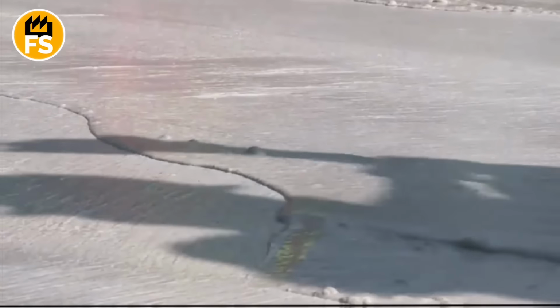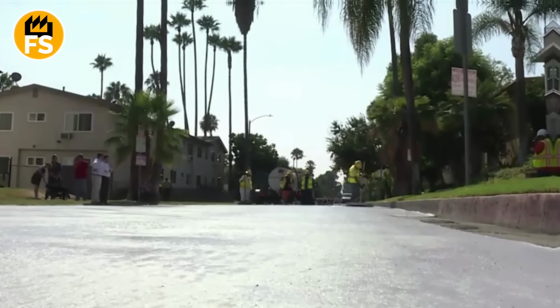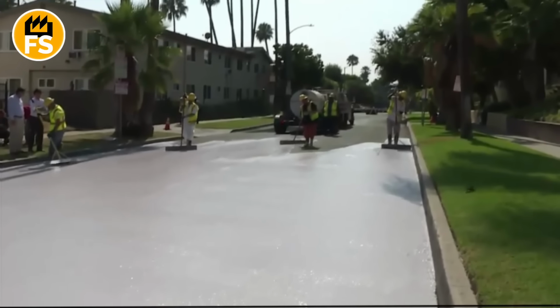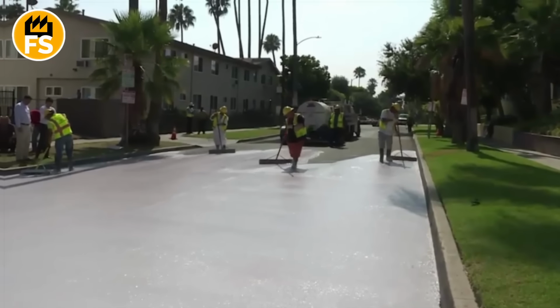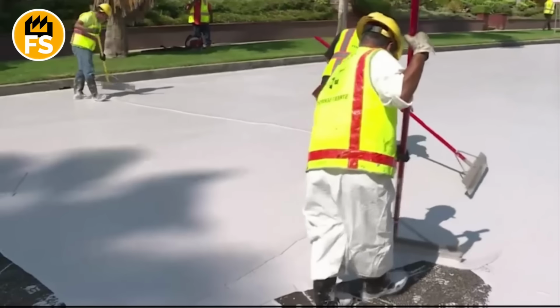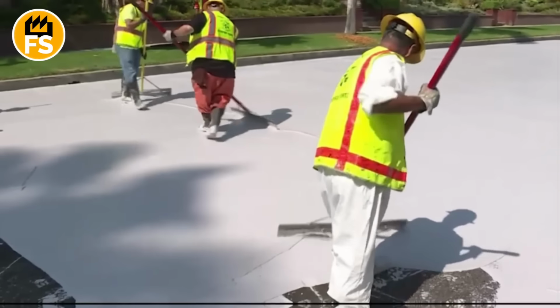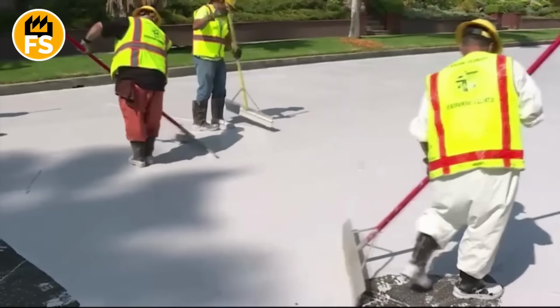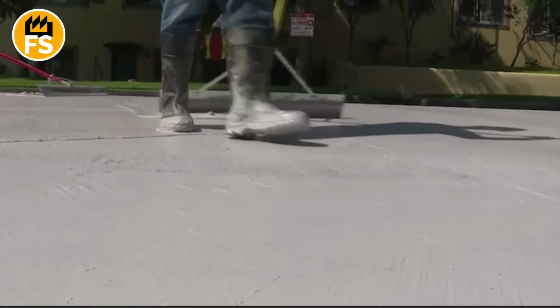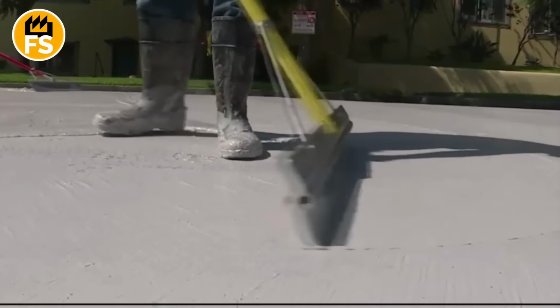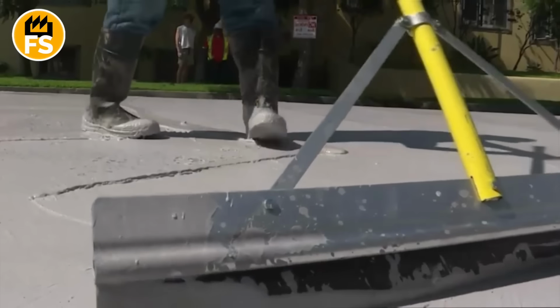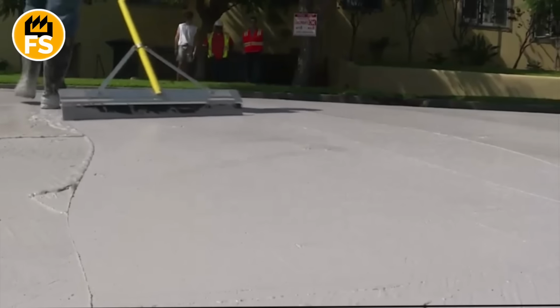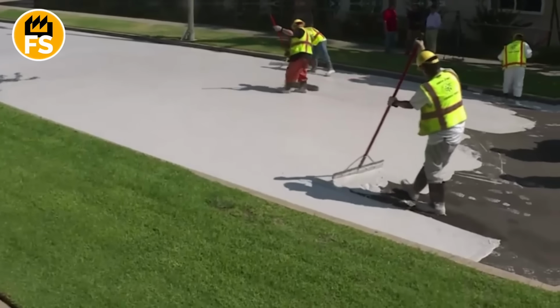There's also data on experimental light reflective coatings being tested in residential areas and near pedestrian zones. On average, such coatings reduce road surface temperature by 10, or even up to 14 degrees, depending on conditions. According to observations, in areas with cooling roads, air temperature at pedestrian foot level also drops by 2 to 3 degrees, reducing thermal load on people and making outdoor stays more comfortable.